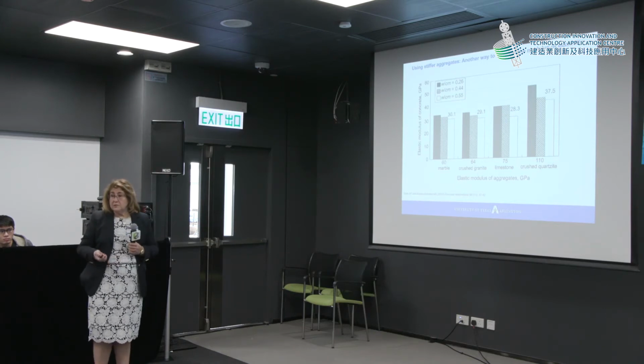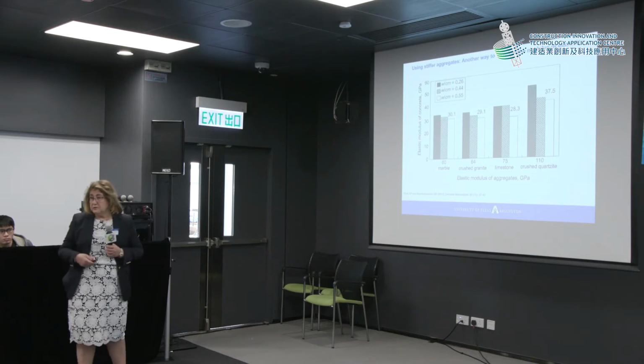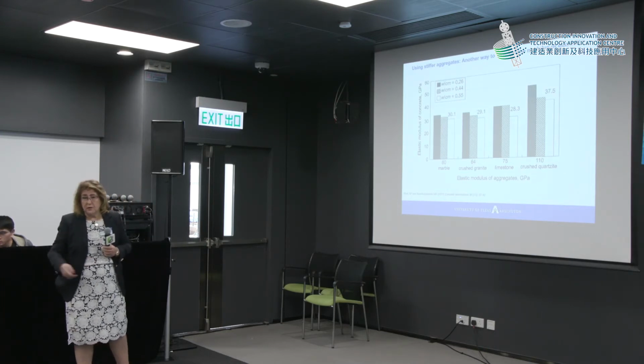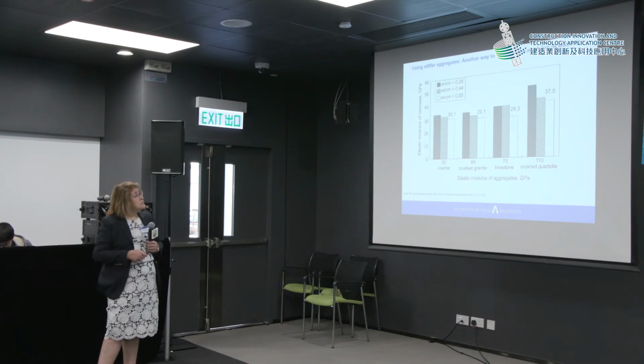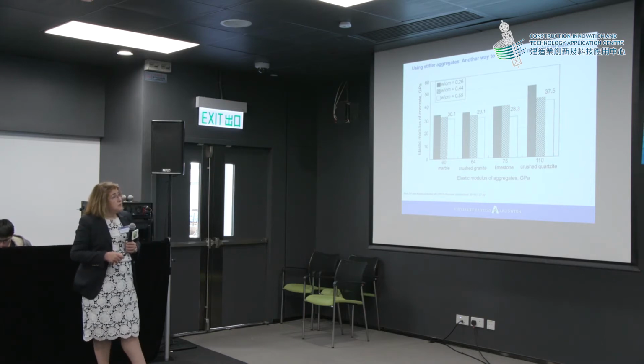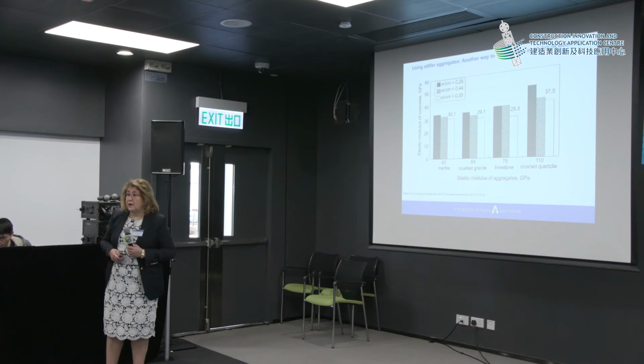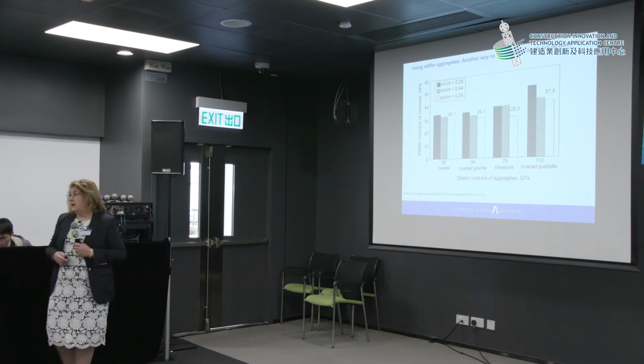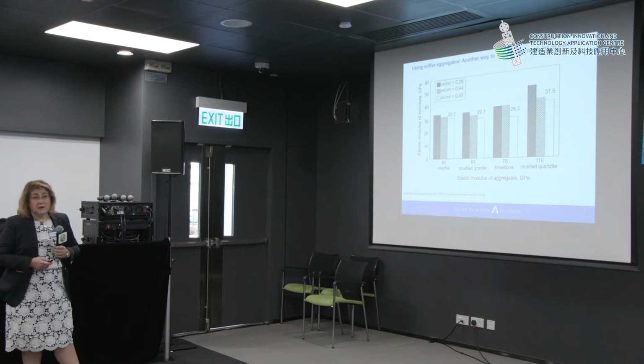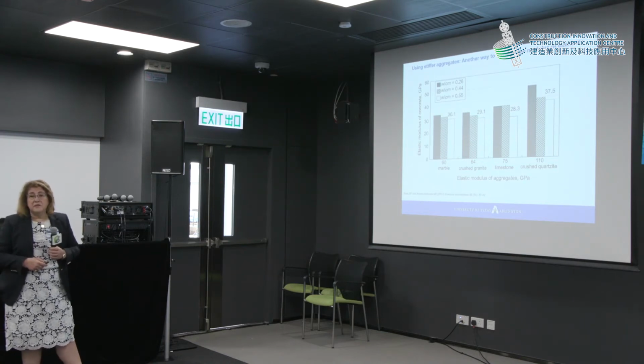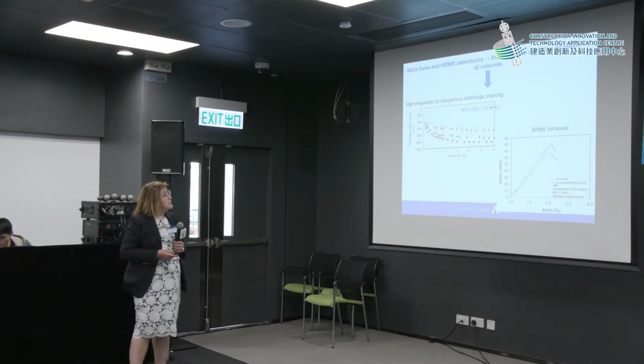Another way of increasing the modulus of elasticity, besides lowering the water-to-cement ratio and including silica fume and all this supplementary cementitious material, is to use stiffer aggregates. But then again, even if we use the stiffest aggregate possible, for example, here, the crushed quartzite, then we can increase the modulus of elasticity using a water-to-cement ratio, 0.26 here, and then the modulus goes, let's say, up to 48. Still, we do not have the desired increase that materials people envision at this particular moment.